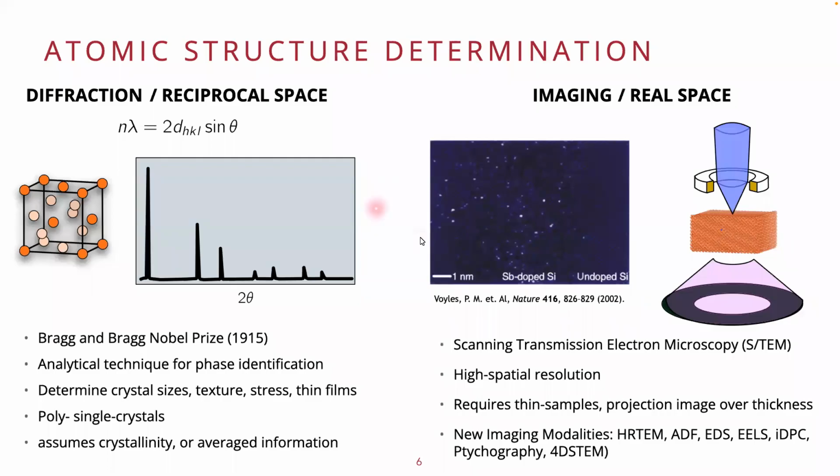The next thing that you might think about is imaging these systems in real space, which you can do in the electron microscope, where now we have truly high spatial resolutions, where you can see small dopants in a silicon film, but we're still actually seeing the projection, right? So we're looking down atomic columns. So we might know that there might be 1 defect or 2 defects within the column, but we don't know exactly where they are or where they relate to one another.